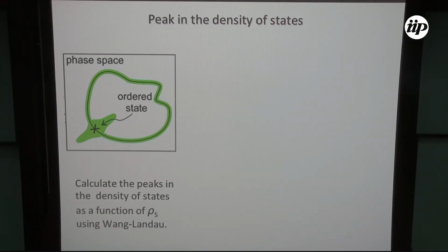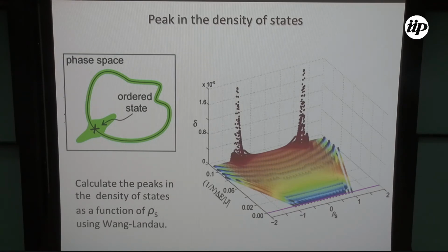Okay, so there's one more thing you can do. If you're not convinced that this is an order by disorder case, because we're doing simulations, you can do this more easily. You can calculate the density of states for your system and see whether this picture here is true. We used the Wang-Landau algorithm to calculate the density of states, and we're plotting here the density of states of the system as a function of the energy, as a function of this rho staggered parameter. So this parameter here parameterizes this curve. You see that when you are at rho equal 1, you have this big peak in the density of states at a temperature of the order of 0.1. This peak is the equivalent of that blob there. What it's telling you is that when you are at this rho staggered, you have all these states available that are not available at any of these other points.